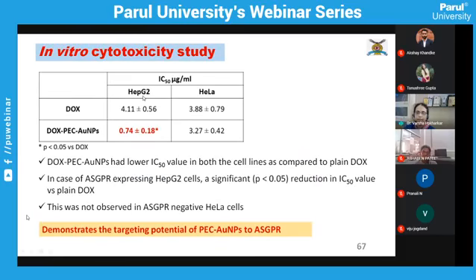Here you can see the IC50 values will help us to understand better. The HepG2 cell lines are the ASGPR positive cell lines and the HeLa cell lines are the ASGPR negative cell lines. Here you can see that DOX has an IC50 of 4.11, whereas DOX anchored onto the pectin reduced gold nanoparticle has considerably lower IC50 values. This is a very significant reduction that occurred when the DOX was loaded onto the pectin reduced gold nanoparticle in the case of HepG2, which is asialoglycoprotein positive. However, in the case of the HeLa cell line, there was not much change in the IC50 value because these are asialoglycoprotein negative cell lines. This essentially demonstrated the targeting potential of the pectin reduced gold nanoparticle to the asialoglycoprotein receptors.